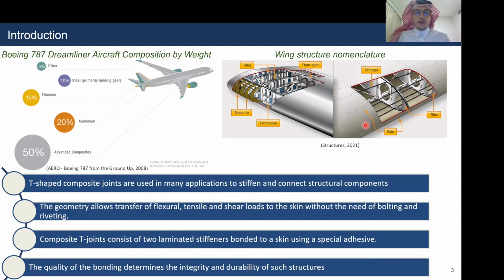So therefore, T-shaped composite joints are used or can be used in such applications to stiffen and connect those structural components. And the advantage of those T-joint structures is that the geometry allows the stresses to be distributed and transferred from the stiffener to the skin without the need of bolting and riveting. And the main components are two laminated stiffeners bonded to a skin using a special adhesive. However, the quality of this bonding determines the integrity and durability of those T-joint structures.